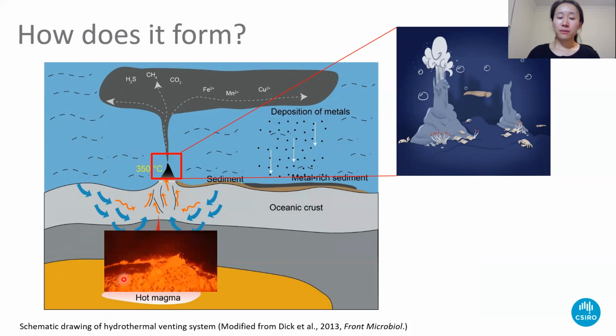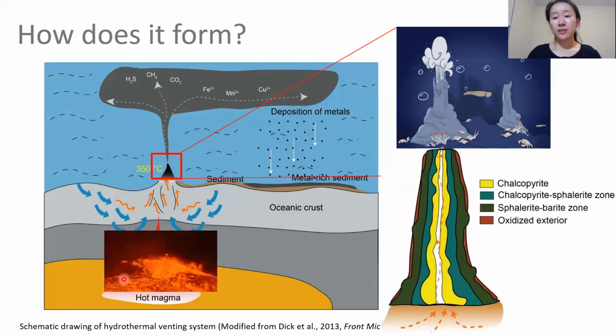The metals can be sourced from the leaching of the oceanic crust and also sometimes contributed by the magmatic fluid during the degassing of the underlying magma chamber. The chimneys usually feature zonation textures with the temperature gradient from high to low from interior to exterior. So usually the chimney features a chalcopyrite interior, which then transits into the sphalerite dominated area and then the sulfate and oxides exterior.